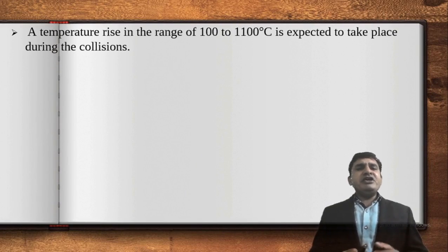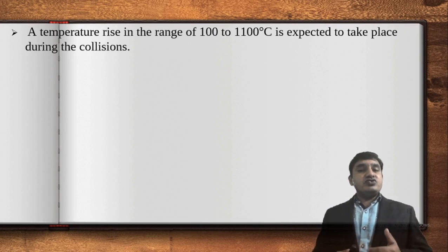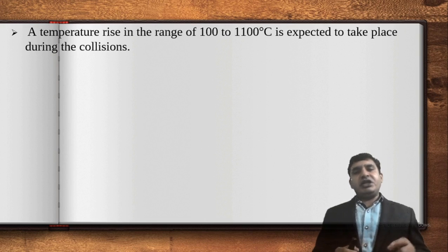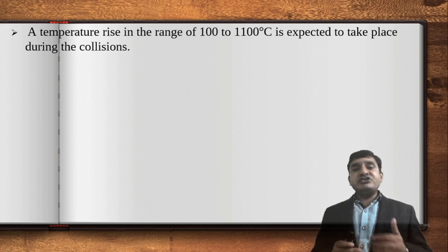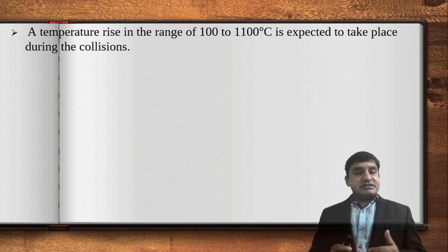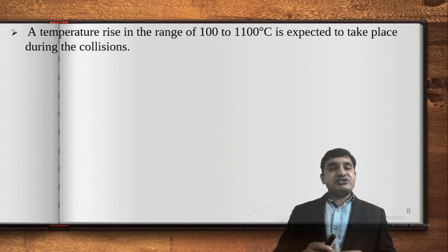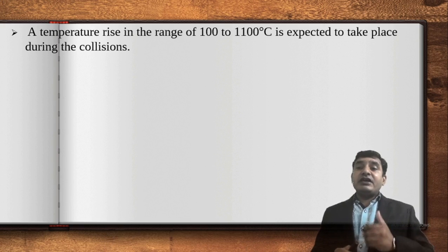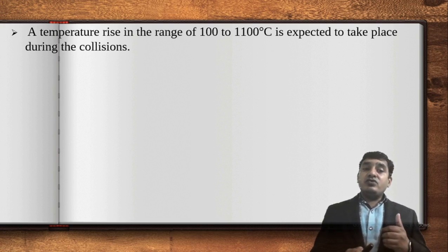Now, a temperature rise in a range of 100 degrees Celsius to 1100 degrees Celsius is expected to take place during the collision, when the cylinder rotates and the balls inside the cylinder rotate. So the temperature also affects the process.